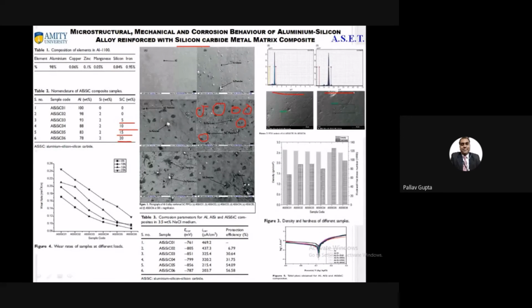So they always try to find out, or they always give problems, like they say you propose a material which is highly corrosion resistant. So that is why we studied this particular class of material in NaCl medium, because whenever a ship is moving in the sea, it has salty water. And if you take sea water from a particular seashore and examine it, it is just parallel to adding 3.58% NaCl in water. So the corrosion test of all these materials, that means pure aluminum, aluminum silicon alloy, and aluminum silicon and silicon carbide particles, were performed in 3.58% NaCl medium.